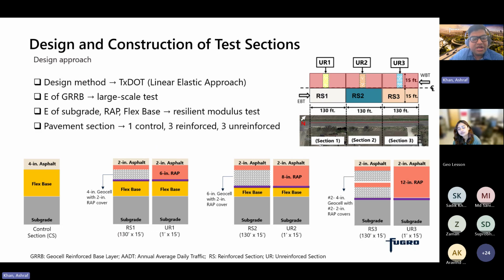But before the construction, we need to do analysis based on TxDOT approach, which is linear elastic approach. And for that, we need the modulus, which was for the Geocell reinforced base layer. We use large-scale test results. For the subgrade, RAP, and flex base material, we use resilient modulus test results. And if you look at the location, we had 3 zones. So we had actually the control section, the existing zone had 4 inch of asphalt, but all the newly constructed test location had 2 inch of asphalt at top of it.